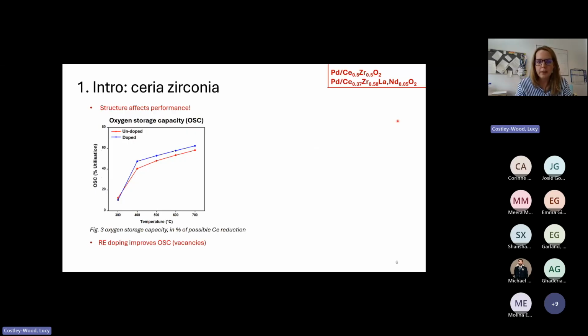However, structure affects performance. If we look at the oxygen storage capacities, we see that for the bare ceria zirconias, the doped is improved over the undoped. The units that we're reporting here are also important. It's percentage utilization. That's because if we want to compare how much we can reduce each of these structures, looking at our formulations up here, one of them has less cerium than the other, and we need to be able to reduce the cerium to remove the oxygen. So if we just compared the raw data, it wouldn't really be a fair comparison. So we use percentage utilization because it allows us to normalize to the amount of cerium. Instead, we're talking about, of the theoretical maximum oxygen that can be removed, how much is being removed.